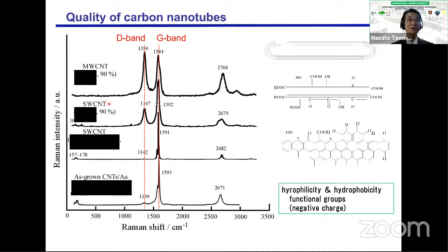These are all single-wall carbon nanotubes, but the quality is quite different. You can see this large D band. However, in this sample, you cannot see any D band. This single-wall carbon nanotube is very expensive. So you can check the quality like this. Basically you can observe the D band, which means lots of functional groups, so the surface is hydrophilic. You can easily disperse this carbon nanotube in solution by sonication. But in this case, there are no defects, so it is very hard to disperse in solution.